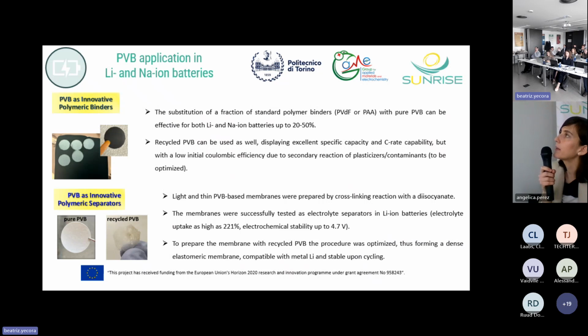In the case of substitution of binders, when working with virgin PVB, it has been able to substitute a fraction of the standard PVDF or PAA with this PVB, up to contents of 20-50%, and these are effective both in lithium and sodium ion batteries. And then the recycled PVB was incorporated, and it can also be used, displaying excellent specific capacity and rate capability, but with low initial Coulombic efficiency due to secondary reactions of the plasticizer contaminants. So this needs optimization, but it's working also.